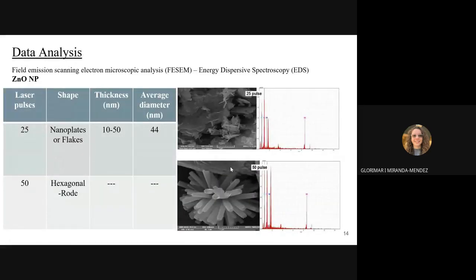They used SEM and EDS. The EDS they used mainly to determine the purity of their nanoparticles, to determine with the zinc oxide nanoparticles that there's only zinc and oxygen present, and with the zinc oxide doped nanoparticles that there's only zinc, oxygen, and aluminum. So with the SEM, they managed to observe a great variety of shapes and also average diameters.